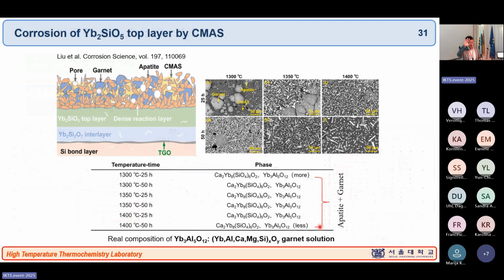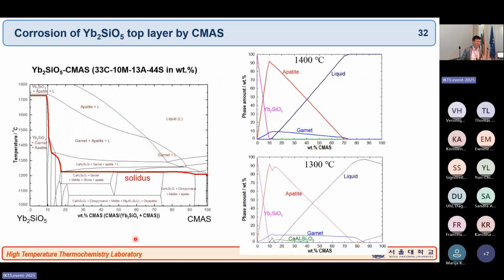But when you put this ytterbium silicate material under this kind of dust condition, people try refractory slag experiments like this. They put in CMAS to imitate that dust material, increase the temperature to 1400 degrees, and did the experiment. They found a different kind of phase formation. So this is the kind of phase diagram we can calculate now. We have ytterbium silicate, Yb2SiO5, reacting with CMAS of a specific composition. And you see this red line again showing the minimum temperature for slag formation. If you're operating above 1250, you can start to have liquid phase formation, forming some solid phases like garnet and apatite, et cetera. So by knowing this phase diagram and using a thermodynamic database, we can change the recipe of this coating material to get more resistance against this extreme environment.